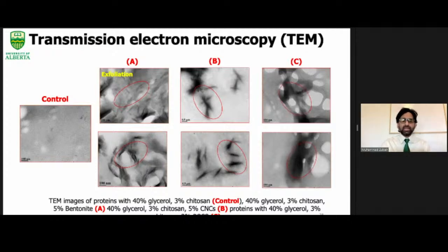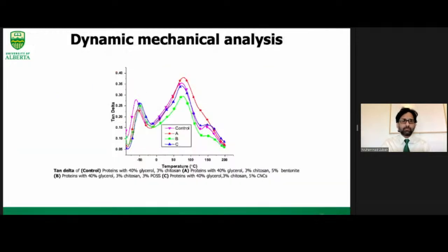Furthermore, dynamic mechanical analysis was performed to see the viscoelastic properties of the films. So in case of nanoparticle added films, we can see that there are three main peaks. However, in case of control, there are only two main peaks.